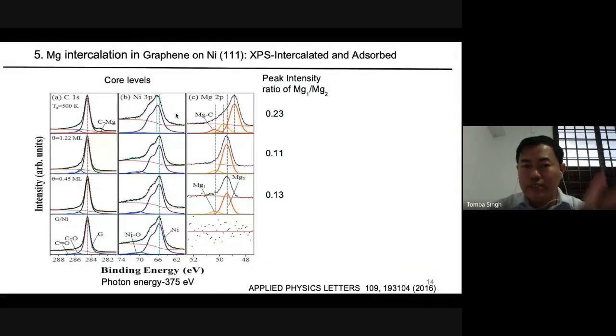So this shows the core level XPS. I just want to mention one point. At the magnesium peak, we found two magnesium peaks. The smaller one is coming from the intercalation, and the high intensity one is coming from the upper layer. So with the variation of the coverage, the density peak keeps on changing. So we can correlate our experimental result with this.